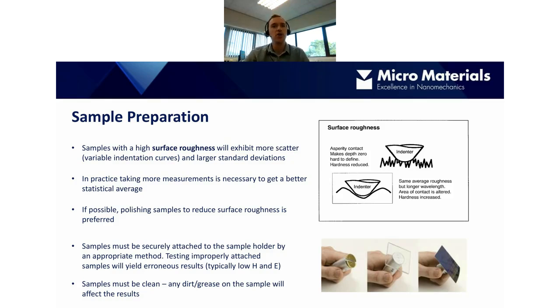So moving on to sample preparation. Surface roughness is a common source of worry. Generally speaking, the lower the roughness, the better. When we indent a material with a relatively high surface roughness, we tend to see more scatter, more variable indentation curves, and of course larger standard deviations, or lower averages in hardness and modulus.